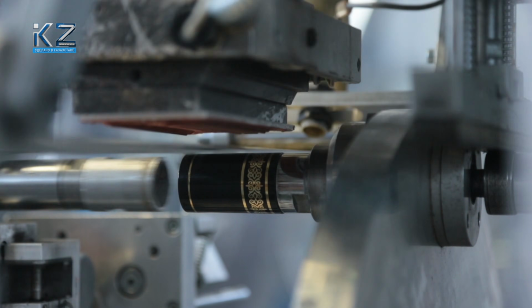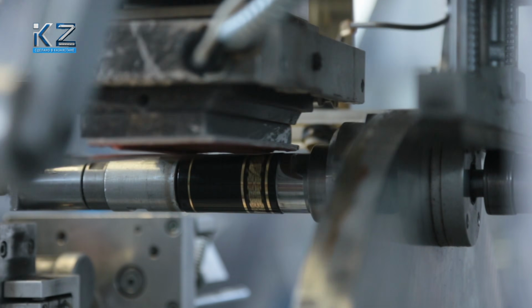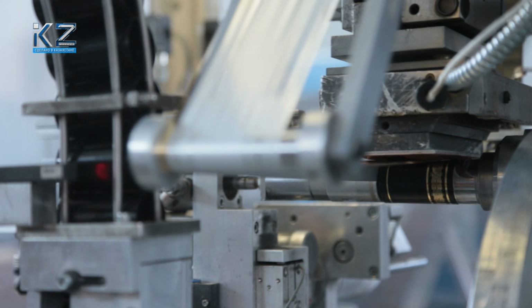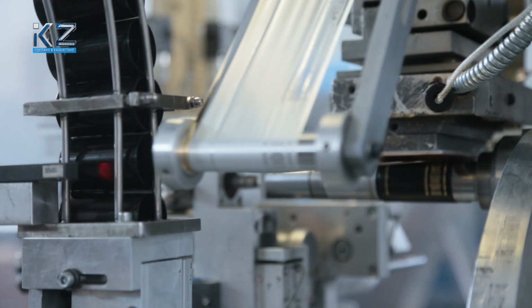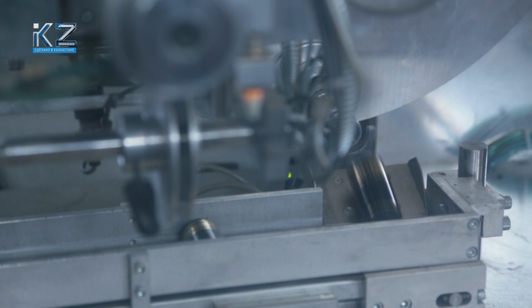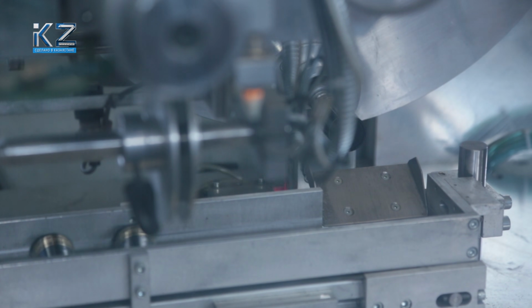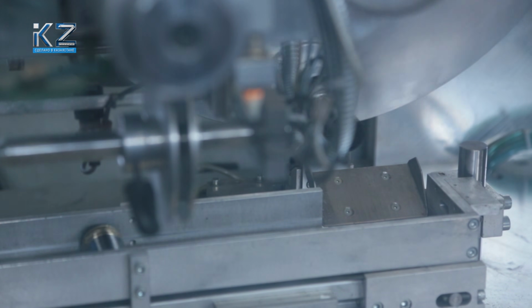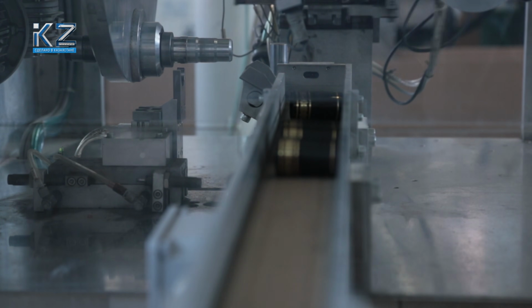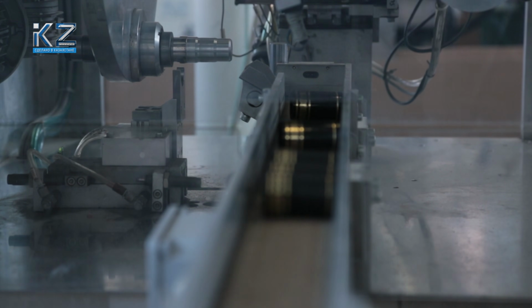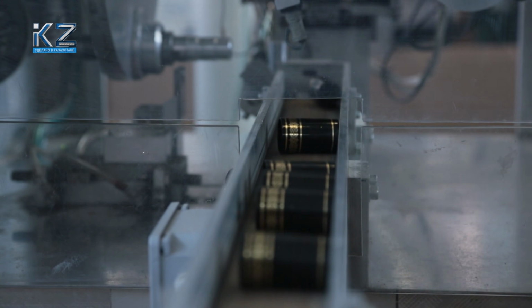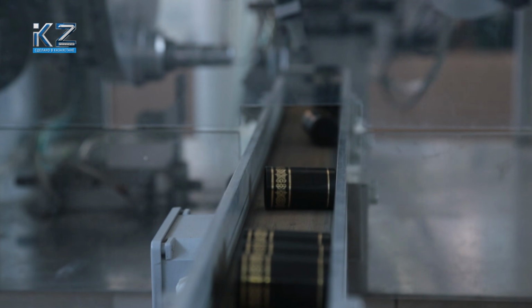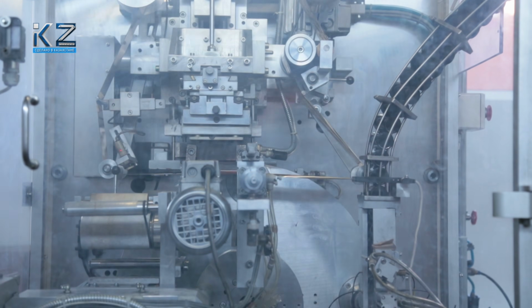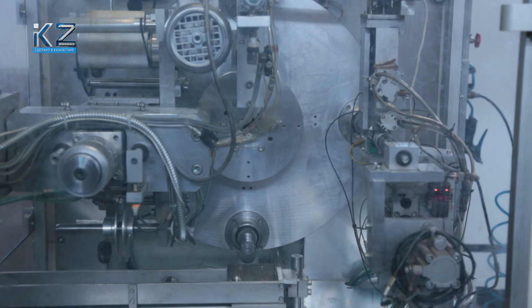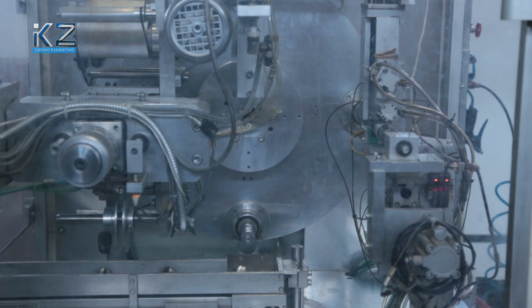The next production stage is the decoration area. Here, 5 machines operate. 4 of them perform hot foil stamping. During the process, a heated die presses foil against the cap material, melting the separation layer and leaving the decorative image on the surface. A standard machine can emboss 2,500 caps per hour, while a high-speed one can handle up to 8,000. Another machine at this facility operates using the screen printing method.